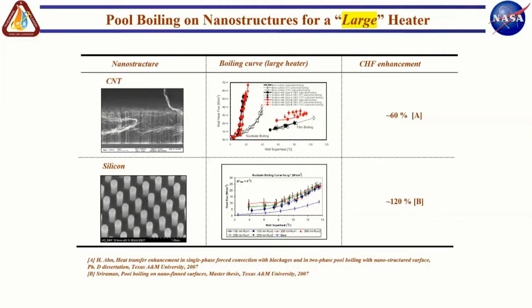And so the top left picture is a carbon nanotube forest that I had shown earlier, integrated with nano thermocouples, so we could measure the surface temperature of the heater. And then, we were also able to measure the wall heat flux by mounting it on a copper block that was heated with cartridge heaters.